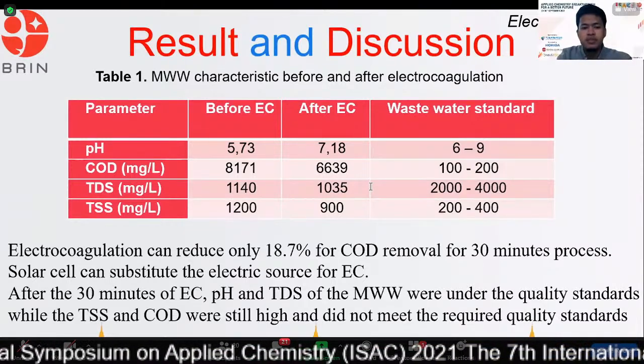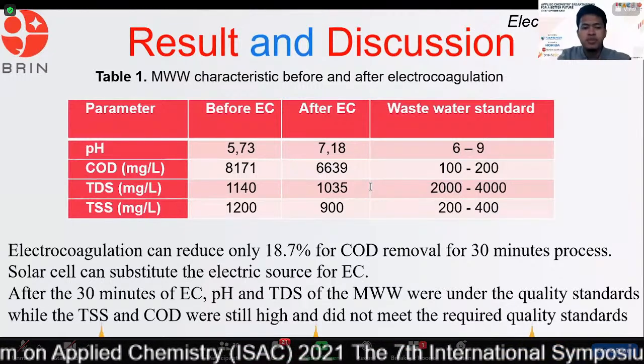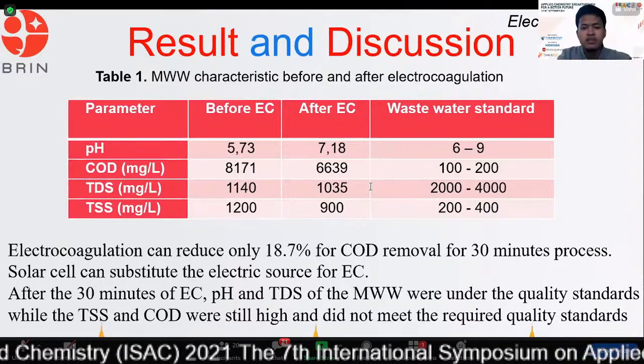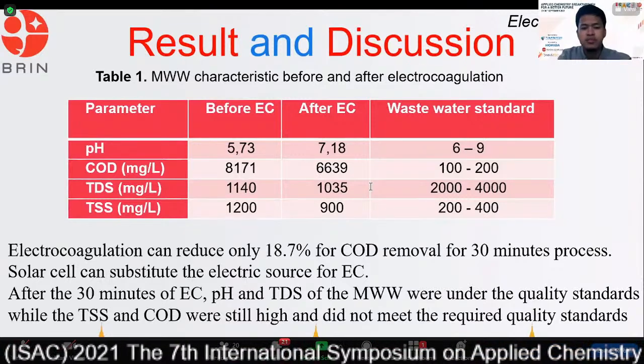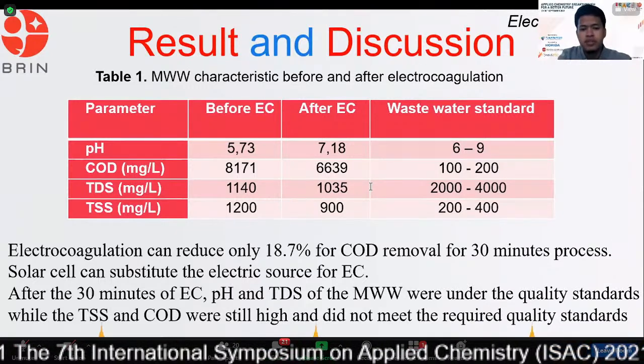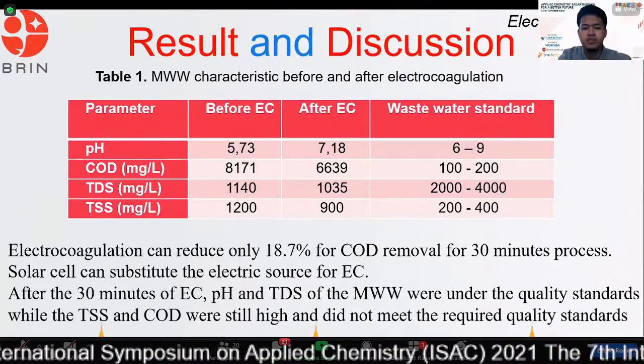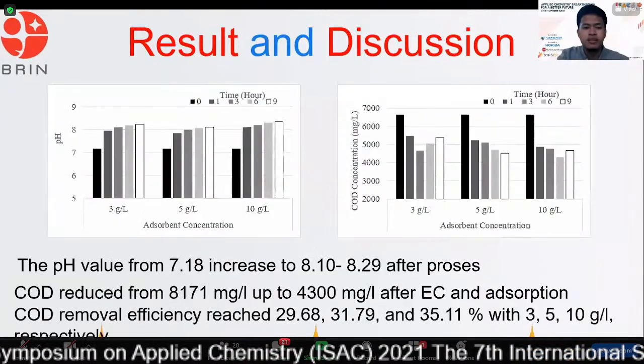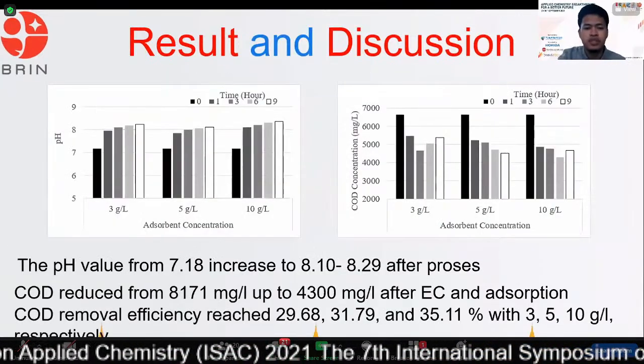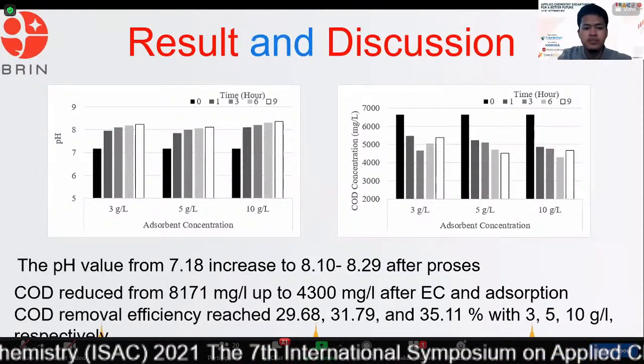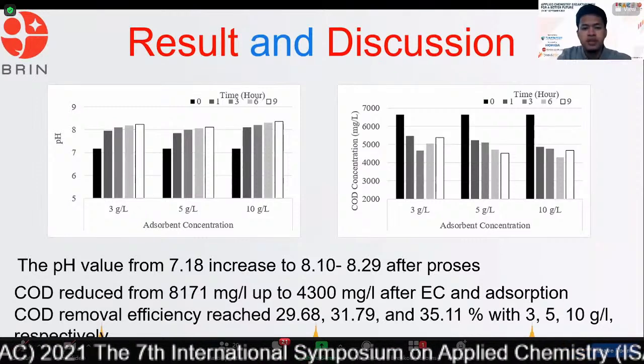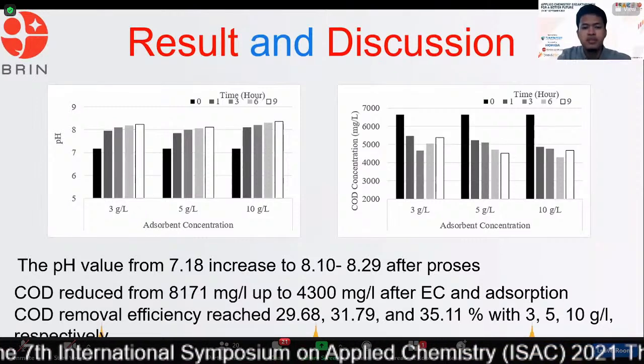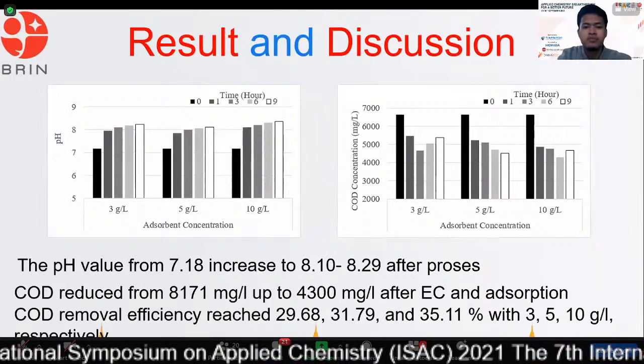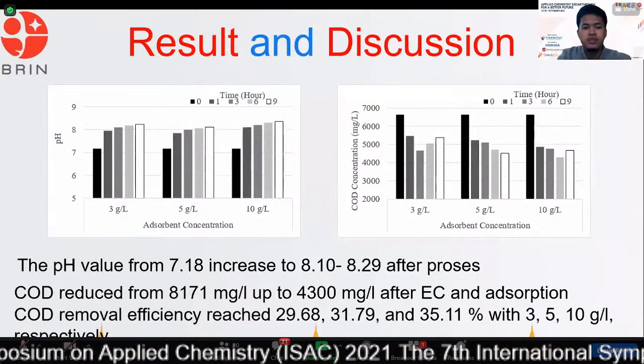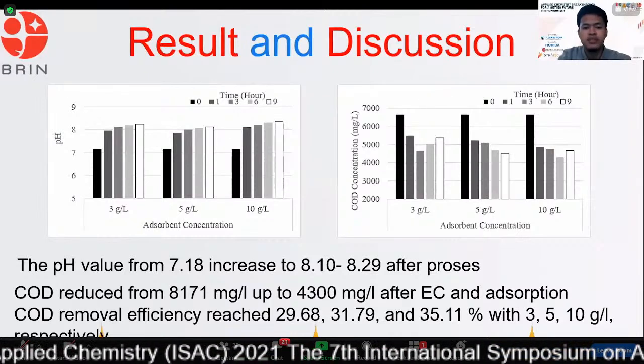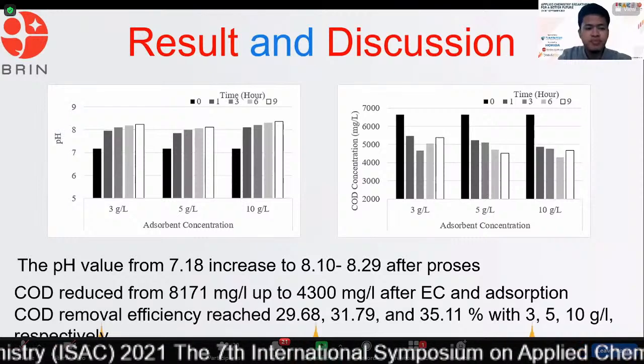And then for the sample, we can see that pH and COD are still high, so we conduct adsorption after the electrocoagulation process. This is the result for the adsorption process. We can see in the figure that after adsorption, the pH increases from 7 to 8. Also, we can see that increasing the adsorption time can increase the pH of the wastewater.